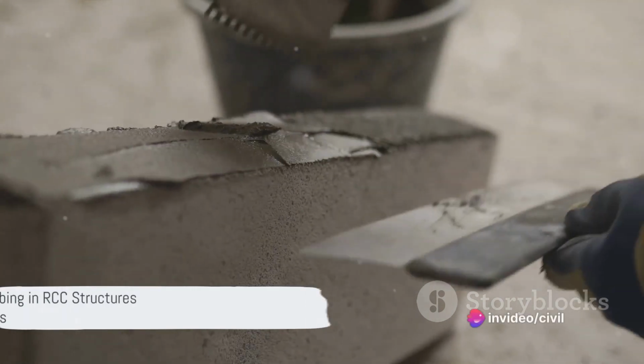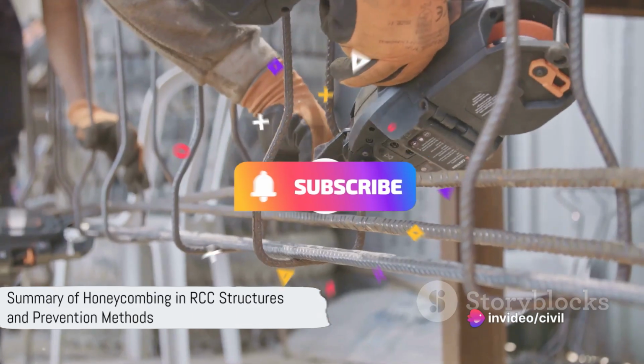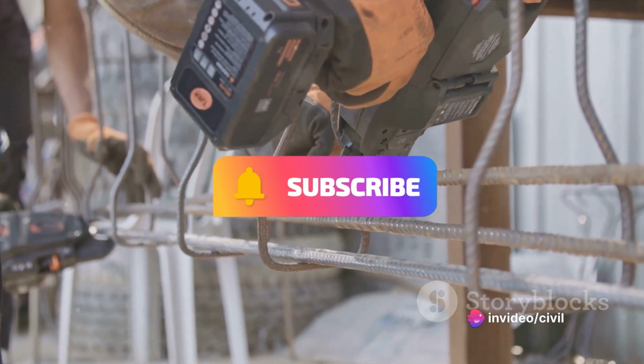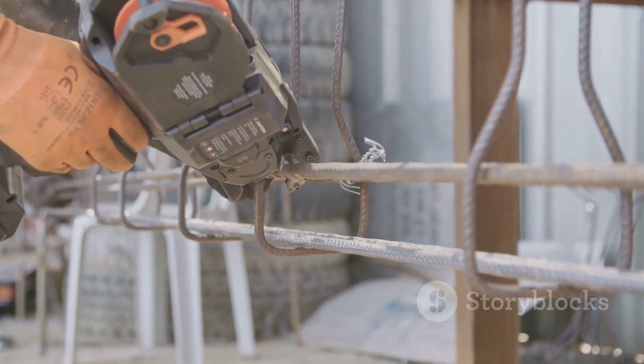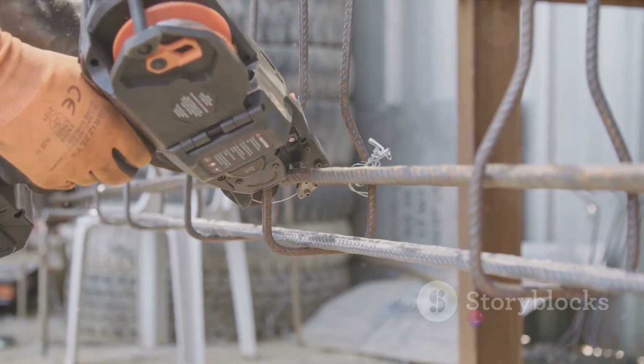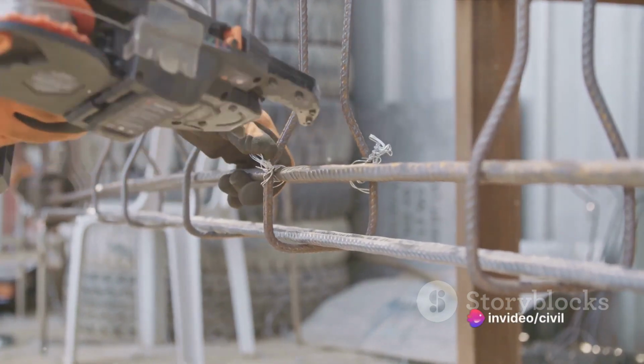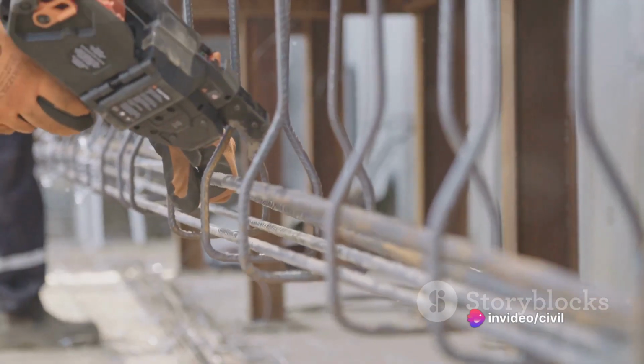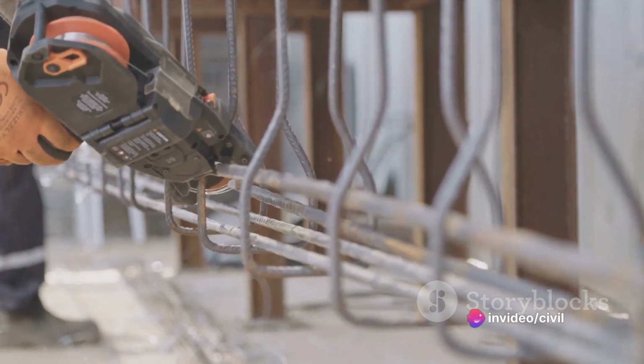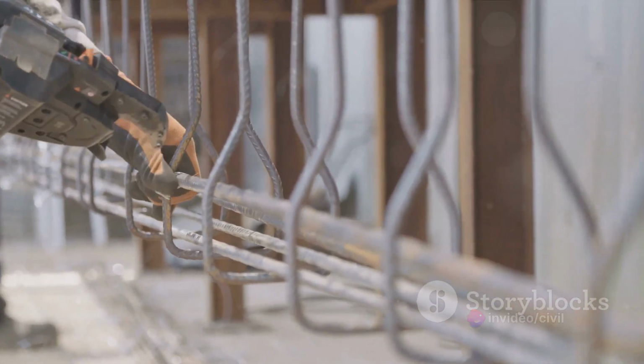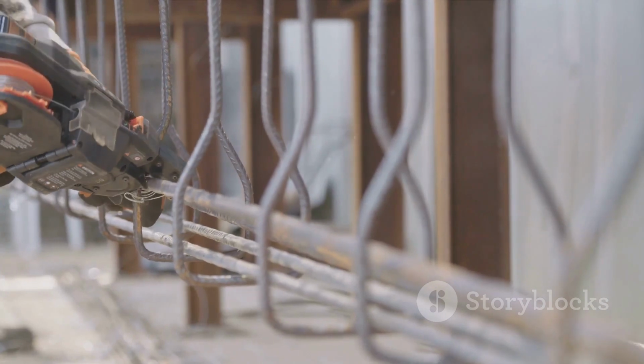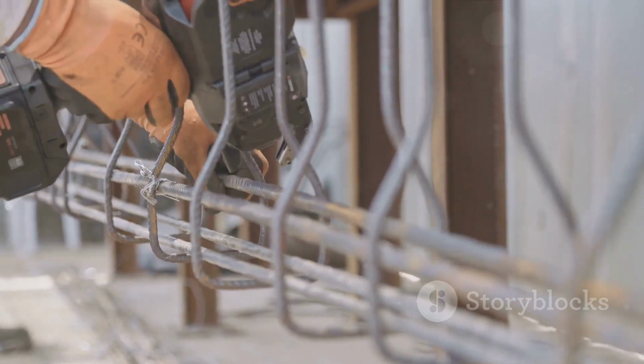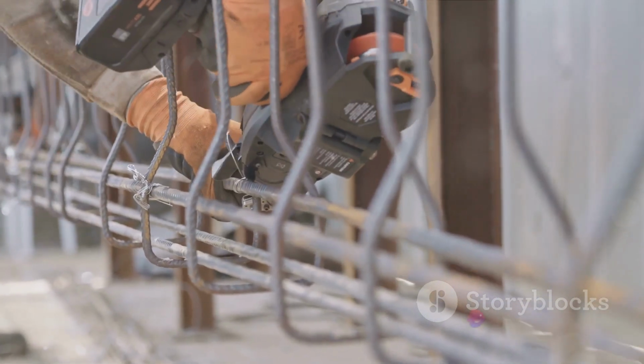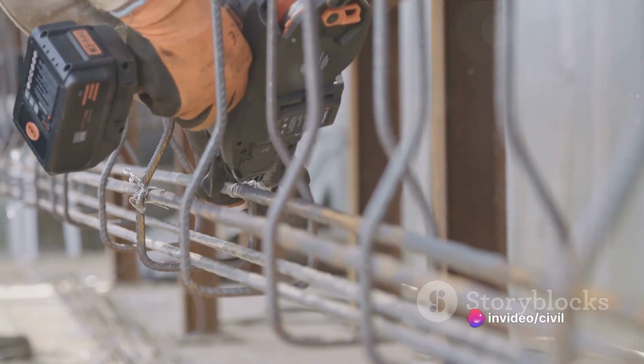In a nutshell, honeycombing in RCC structures is a phenomenon where voids and gaps appear on the concrete surface, resembling a honeycomb. It is caused by factors such as improper vibration, incorrect or inconsistent concrete mix, use of large aggregates, and improper placement of reinforcement bars. However, it can be prevented by ensuring proper vibration, using a consistent, well-mixed concrete, limiting the size of the aggregates, and placing the reinforcement bars properly.